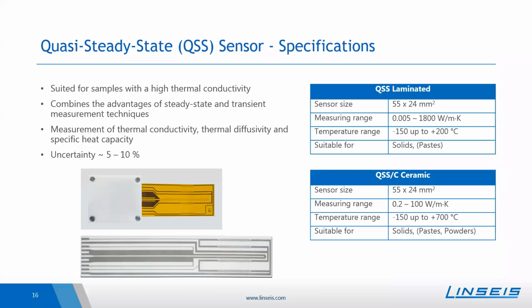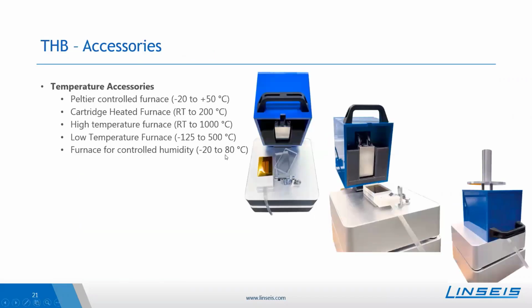A further question which was asked is why one needs a furnace if we have a wire inside the sensor. The wires within the sensor heat the sample only locally, so they increase the temperature of the sample by a few Kelvin, typically between 1 to 4 Kelvin, so that the power of the sensor is not enough to be able to control the sample temperature. It brings only a small disturbance into the material. Because of that, it's necessary to have an external furnace to be able to perform temperature-dependent measurements, so that the sample and also the sensor are at the target temperature, and then the sensor is able to heat up the sample locally by a few Kelvin for the evaluation of thermal conductivity.